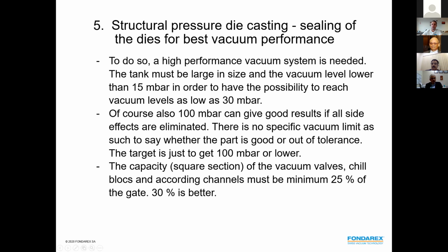So the square section of chill blocks, of vacuum valves, channels, and so on, they also have to be according to the application. So if I have a structural part which has 1000 millimeter square section on the gate, we should have at least 25 to 30% of it on the venting system as well. So that means maybe 300 millimeter venting, and therefore also to guarantee, if we measure good vacuum, that really the air comes out of the cavity.